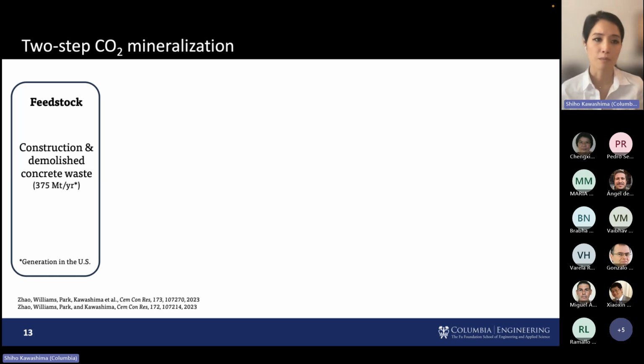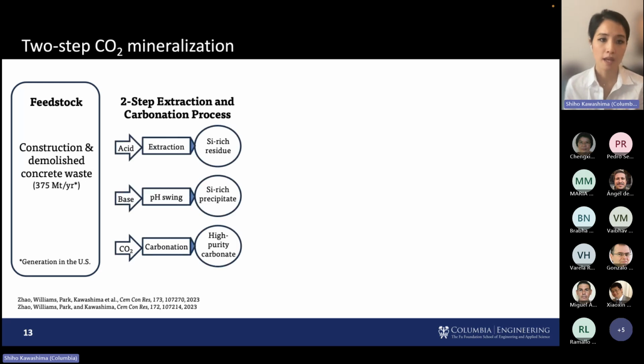So in our work, we employed a two-step CO2 mineralization scheme. And so what does this mean? You start off with your feedstock, which in our case is C&D concrete waste. And then we employ this two-step extraction and carbonation process. Basically what this means is we employ a pH swing. First we introduce an acidic source, and that lowers the pH, and that allows us to extract calcium. And then what you have is this leftover silica-rich residue. So you should be thinking, okay, that is a source of an SCM. And then you introduce a base, and that increases your pH. And from there, you can start to remove additional impurities, so remaining silica, remaining iron, alumina, and that creates the secondary residue, what we call the precipitate.